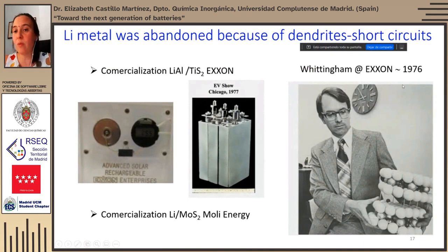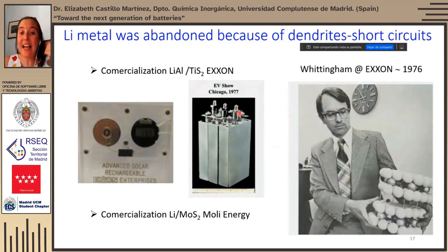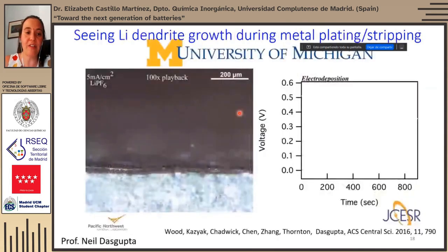Actually, Professor Whittingham, who proposed the lithium titanium disulfide battery in the 1970s while he was working at ExxonMobil, they commercialized their batteries with the lithium aluminum alloy anode, as well as Moli Energy commercialized lithium molybdenum disulfide batteries. And they had to withdraw their batteries from the market very fast because there were always problems of short circuit. And this is because of the dendritic growth of the lithium.